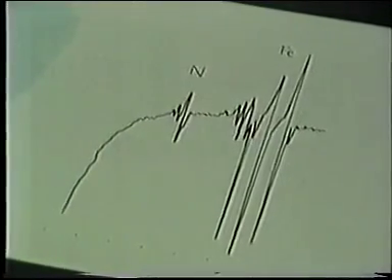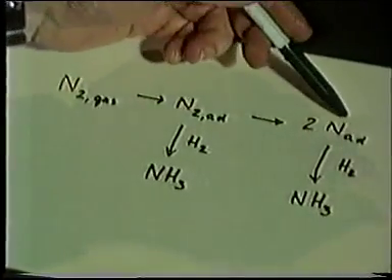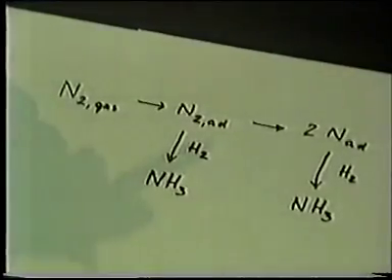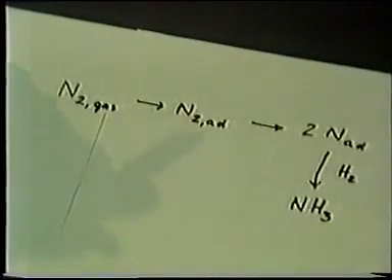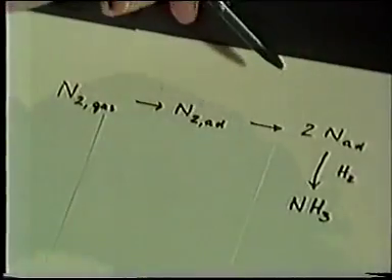This brings us back to our question of the reaction mechanism. We have now demonstrated that the concentration of the atomic nitrogen species is below the saturation value, and this excludes the associative reaction mechanism. We have thus demonstrated that the reaction proceeds through the dissociatively adsorbed nitrogen, which is then hydrogenated.